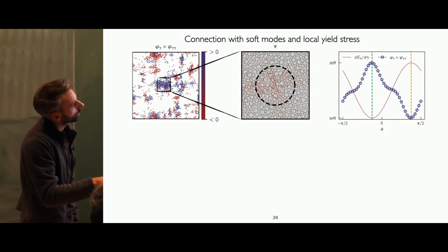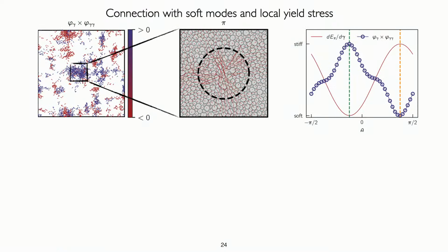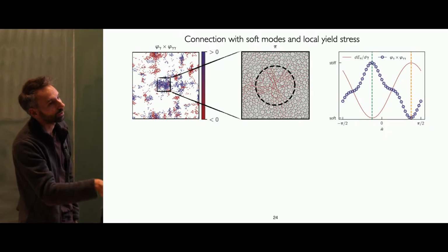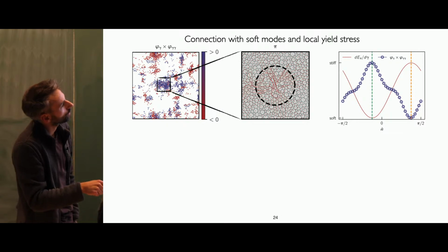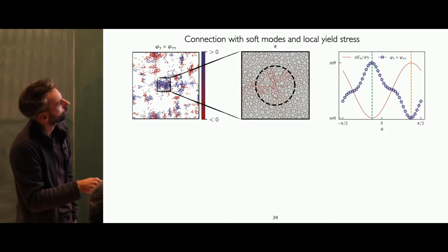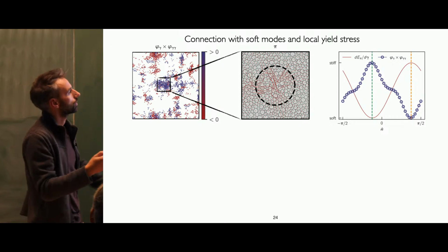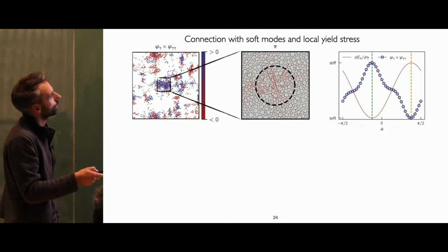And it's what you see in red. It's normalized between the softest, which will be negative, and positive stiffening. What you see if you compare it to the product is that regions with the blue product correspond to regions where the mode will soften the most, so where the change of energy will go down. And so you can distinguish two poles, which will be like the most favored direction and the least favored direction. And those actually follow some symmetry. This is one strain derivative, so it will follow the symmetry of the stress. And here there will be a combination between symmetry of stress and symmetry of elastic constant.